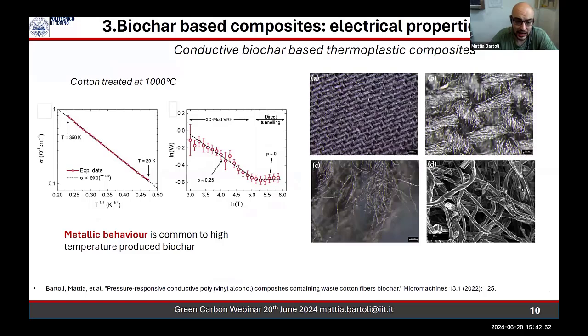Same thing for other more exotic materials, like cotton. We studied cotton because it's basically cellulose-based. And as you can see, we can obtain similar carbon fibers. Also in this case, we observe a metallic behavior. We also saw that we can use them, even if they are quite fragile at this temperature, in a tissue-like biochar-based material. So we make a net, we preserve the net, we pyrolyze it, and we use it as a conduction bed.